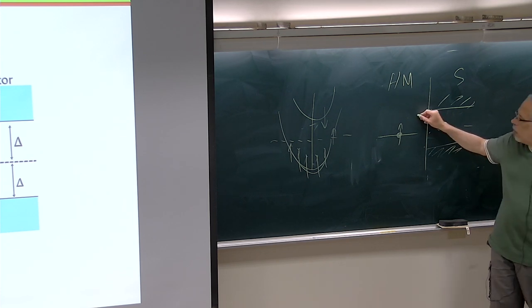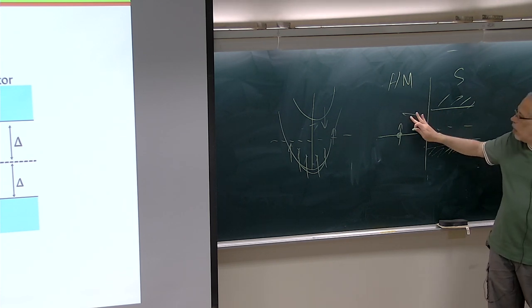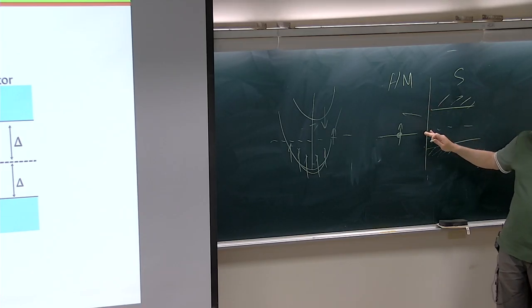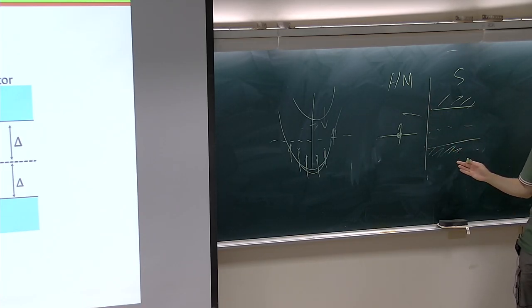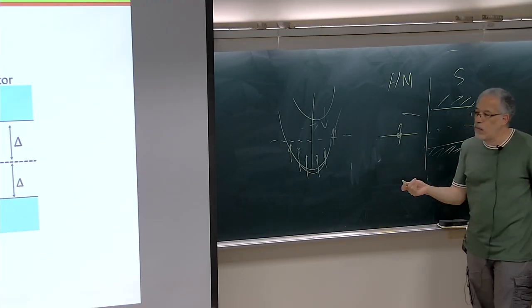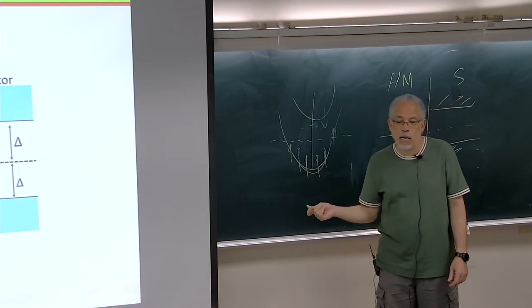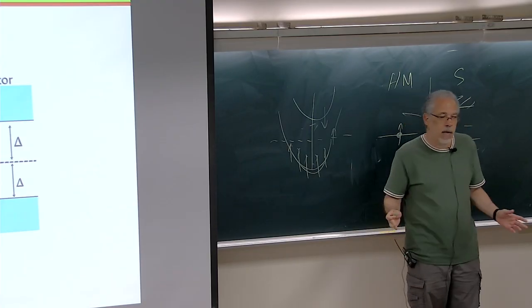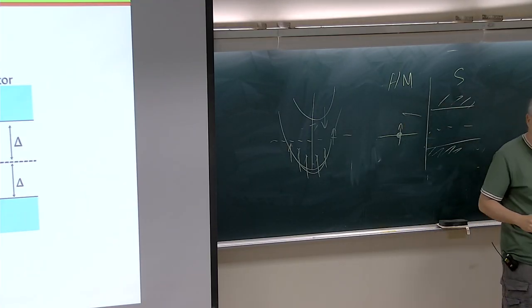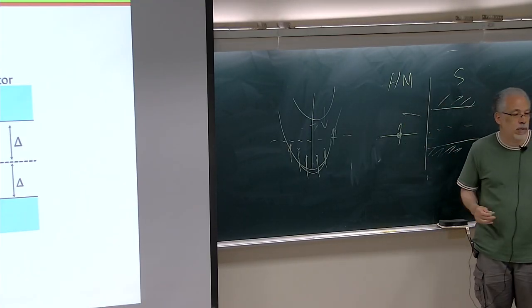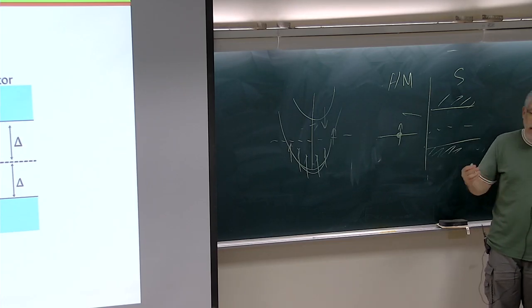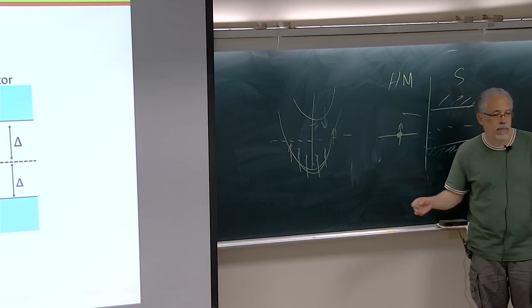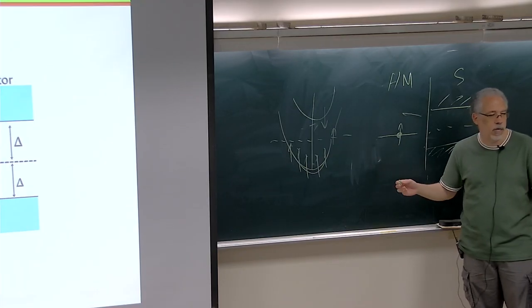So they will have to be reflected, normal reflection if the energy is high, but at this point the Andreev reflection is suppressed. So you can measure this Andreev reflection, and if you have very good Andreev reflection, it means that you don't have any spin polarization. If your Andreev reflection starts to be suppressed and becomes smaller and smaller, it means you have more and more spin polarization.